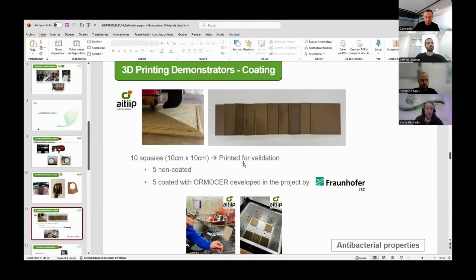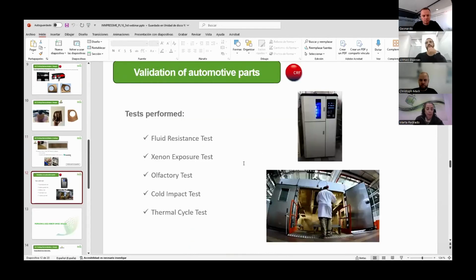Instead of printing a lot of demonstrators, because I just mentioned it was quite difficult, what we did is to print these squares that you can see here in the picture, and they were tested with and without the Ormocer coating developed by Fraunhofer, which confers antibacterial properties. Here you can see the list of the tests that were performed, and in general, the material shows good mechanical properties. This grade was identified amongst the others to have the best compromise in terms of physical and mechanical profile due to the characterization that was done previously. Also, the cold impact and thermal cycles confirm this assumption.